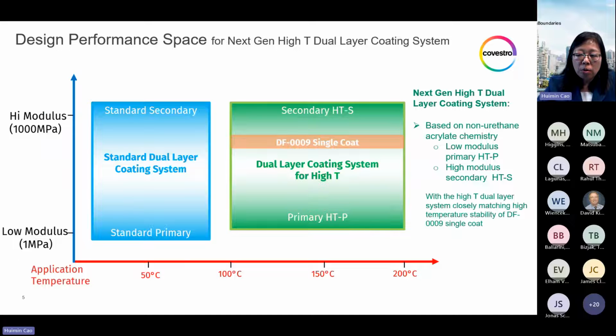Here is how we mapped out the performance space of this new dual layer coating system. It should cover the same high temperature space as the single coat DF-0009, from 100 degrees C to 200 degrees C, with the primary, HTP, designed at a low modulus level, but slightly higher than the regular primary. This is to balance the thermal performance and the microbending performance. The secondary coating, HTS, is designed to the same high modulus level as a standard secondary coating. And this is to benefit both the thermal performance and the microbending performance.